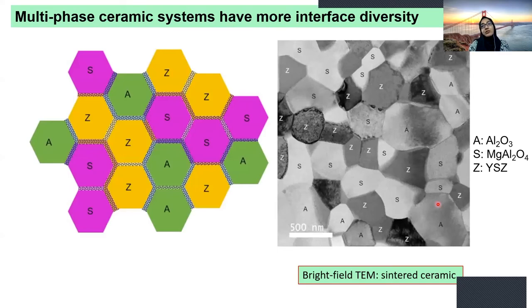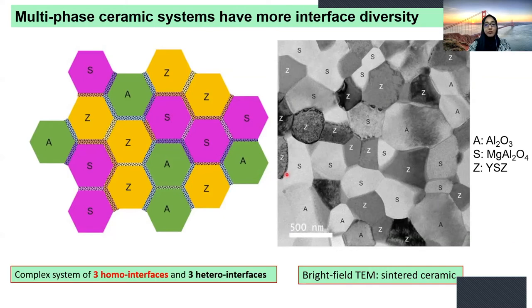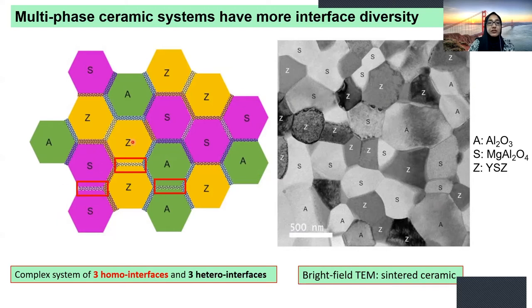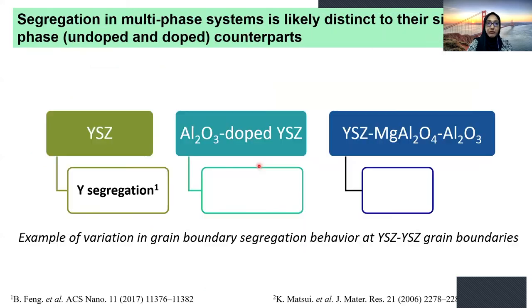As you would expect, multi-phase ceramic systems have a huge variety of interfaces depending on how complex your system is. For our system with three phases — alumina, spinel, and YSZ — what you are seeing on your left is a schematic diagram of the different interface varieties you would expect, and on the right you are seeing an actual Brightfield TEM image of one of our sintered samples showing a huge diversity of interfaces. This complex system contains three homo interfaces — spinel-spinel, YSZ-YSZ, and alumina-alumina — and three hetero interfaces between YSZ-spinel, YSZ-alumina, and alumina-spinel.